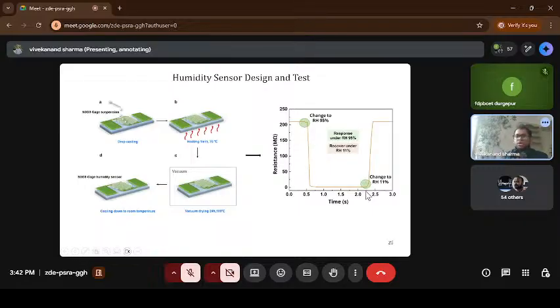When we change the relative humidity again from 95% to 11%, it means that there were very few water molecules present surrounding the sensor. In absence of water molecules, I will say vapor, because this water was present in the form of vapor, not in liquid or solid form. So when the relative humidity changed from 95% to 11%, the sensor becomes an insulator, and its resistance suddenly increases up to maximum 200 mega ohm. So this represents the response and recovery cycle of this sensor. It was pretty fast, with sudden decrease and sudden increase of the resistance.